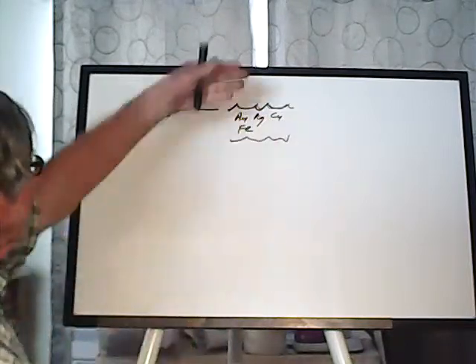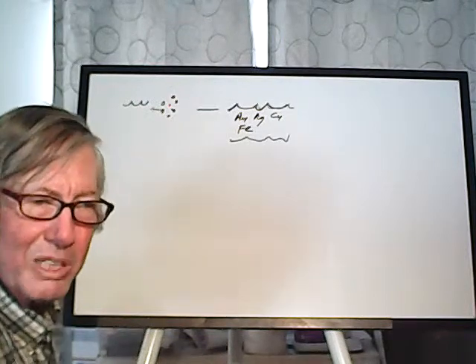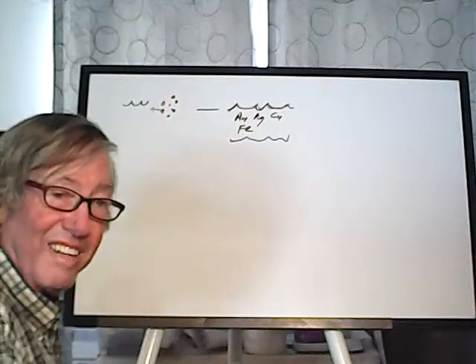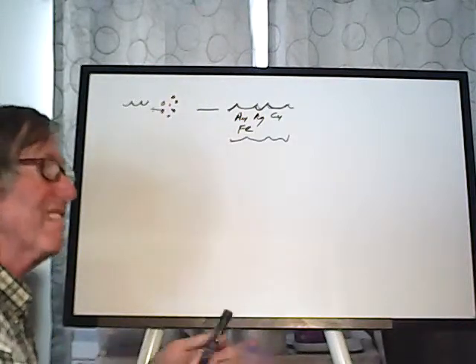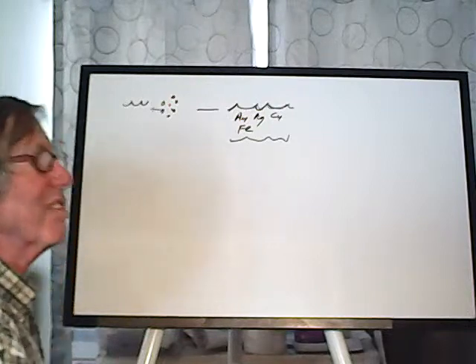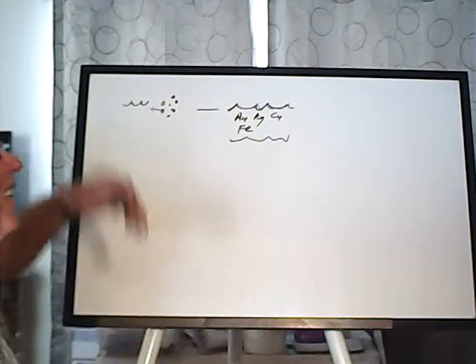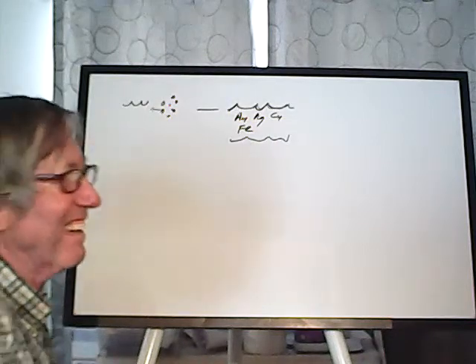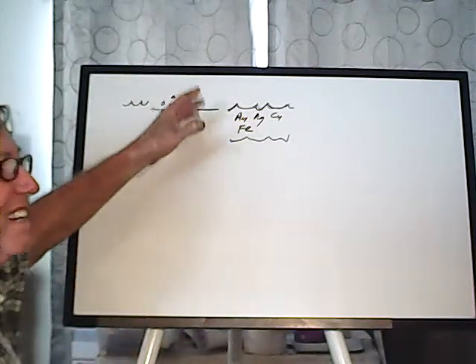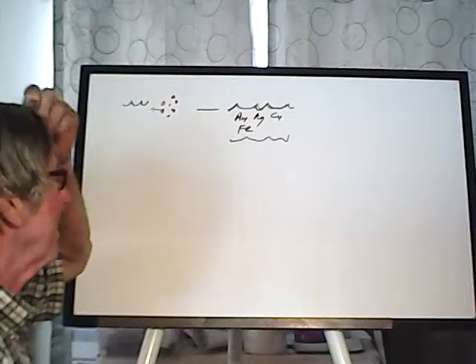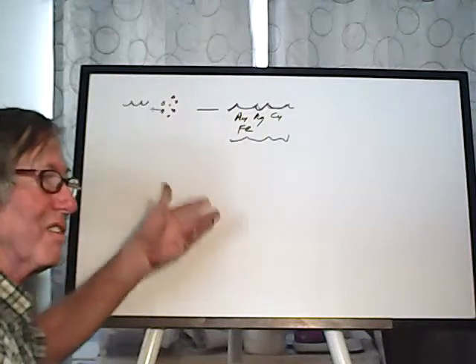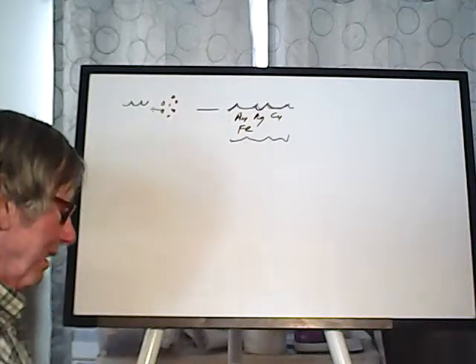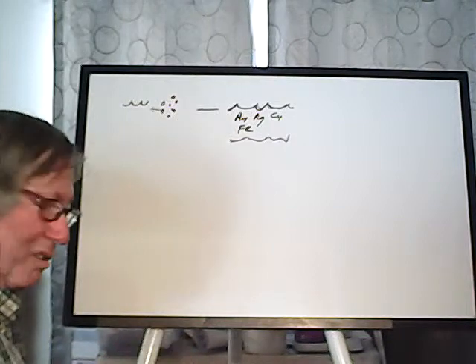So anyhow, this leach solution contains a number of dissolved minerals in it. One of the good things about cyanide is it's fairly selective. It tends to not dissolve everything under the sun. You certainly wouldn't want something that would dissolve silica or feldspar or anything like that. Luckily, nothing that'll do that is cheap and simple anyhow. So, in our case, we're using a thiosulfate-based leach, but you can also have a cyanide leach, which is, of course, the most common one.